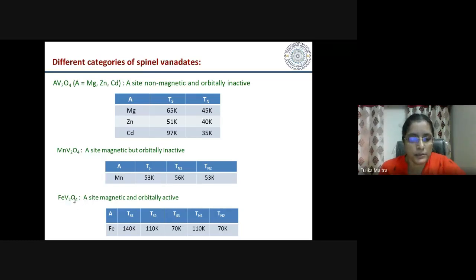And the most interesting one is this FeV2O4, where the A site is both magnetic and orbitally active. Fe is in +2 state, so it's also orbitally active. So here we see that there are 3 structural transitions and 2 magnetic transitions. So there are several structural and magnetic transitions in this compound because of competition between various degrees of freedom.